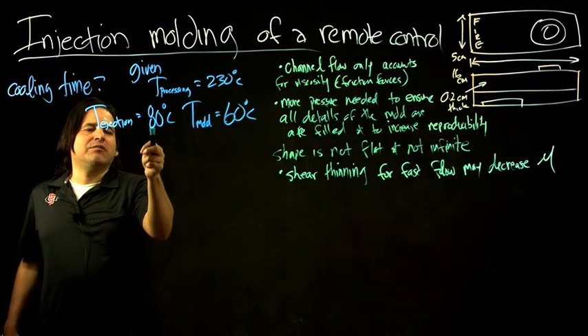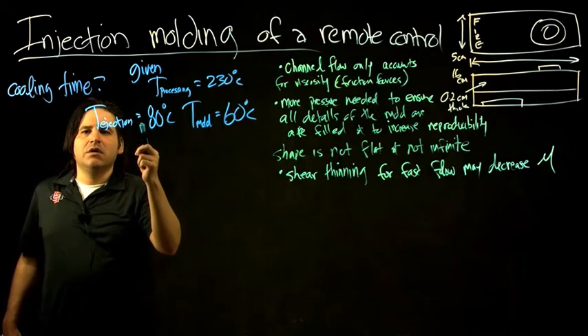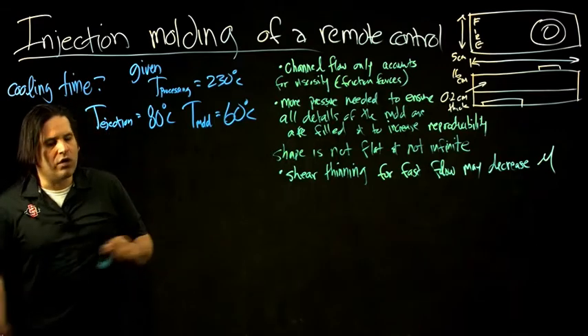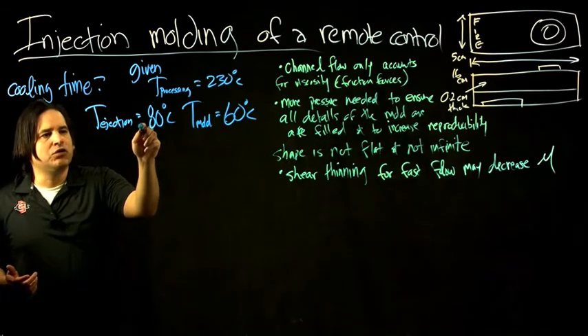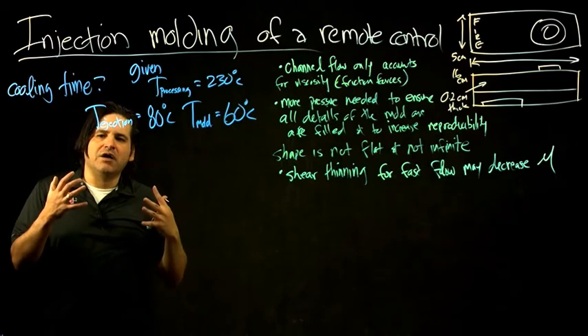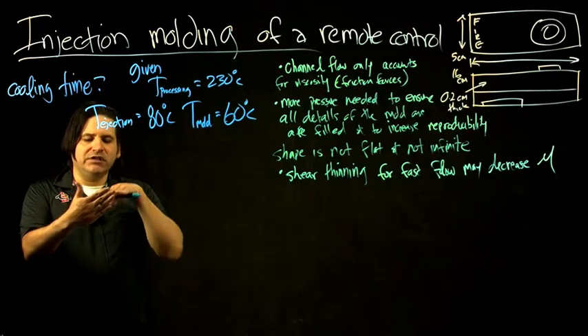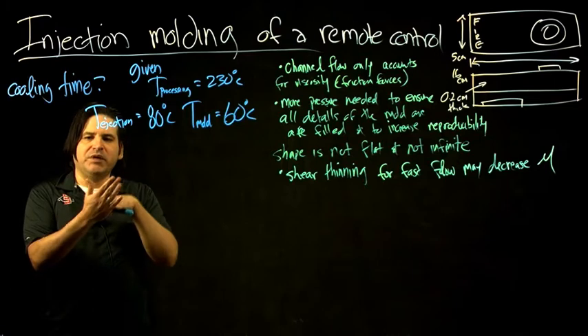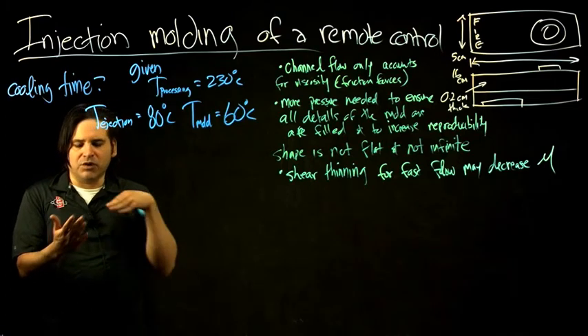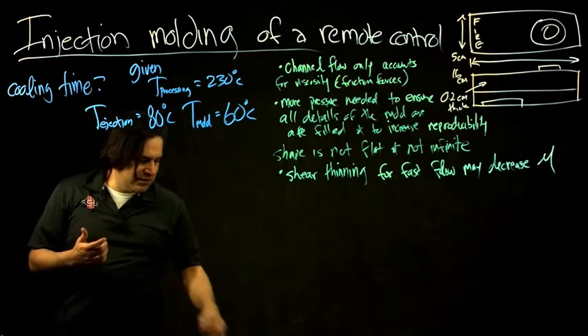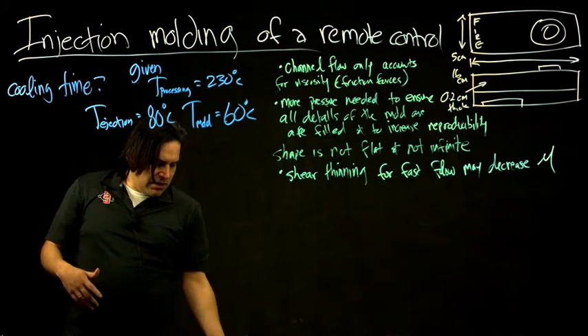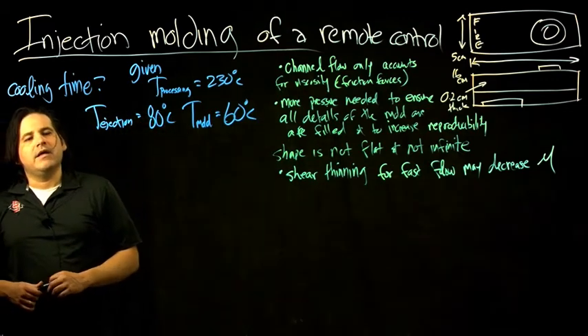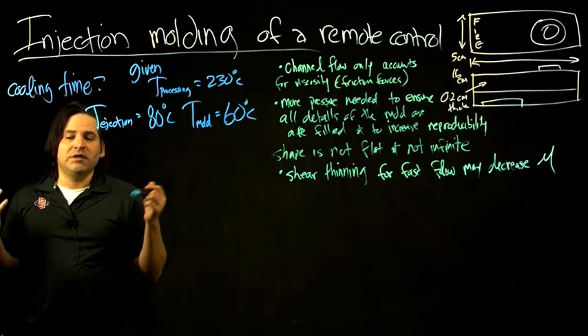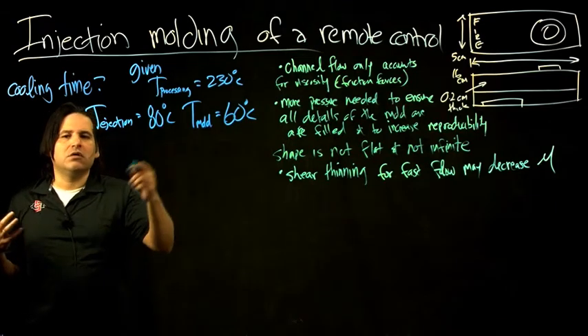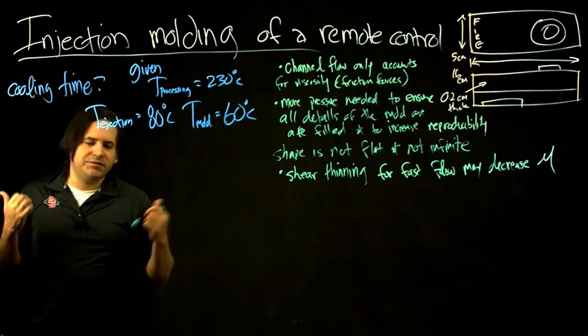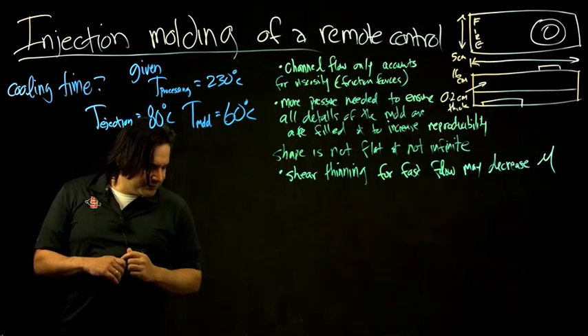So the question becomes, what is the maximum ejection temperature I can use before it causes problems? One problem would be if it's too warm, the material is too soft. And when you eject it using ejection pins, most of the time, those pins will cause problems on the part, either punching a hole in it or causing a deformation if it's too warm. Warm is good because it takes less time to cool, but it's not ready to be ejected. So there's an optimum there.